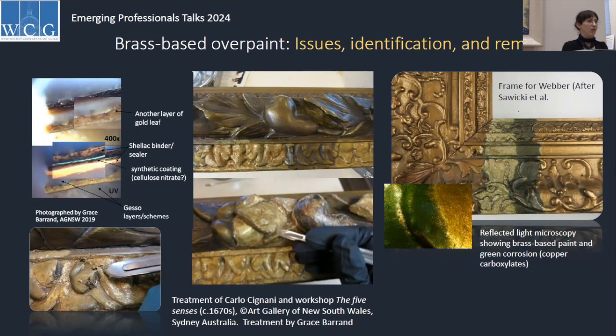At the Art Gallery of New South Wales, we had a huge number of frames that were systematically overpainted, so we had a very large proportion of our collection that were in that state. The overpaint, as you can see here, significantly obscures stylistic distinctions between gilding finishes and ornament definition, and potentially compromises the structural stability of gilding layers. If they're very thick coats of paint, they'll place mechanical stresses on underlying gilding. And with time, the brass-based overpaint oxidizes, and this presents a number of different challenges.